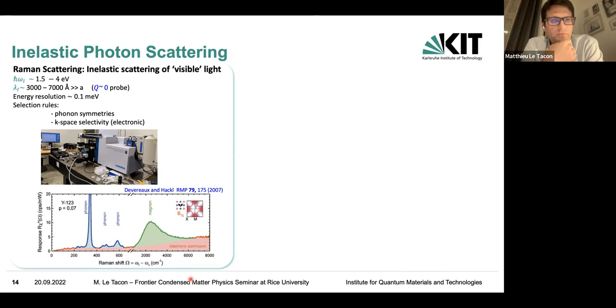The energy resolution is very good. I mean, it's like 0.1 milli-electron volt, and we do have selection rules which allow us to assess the symmetry of the excitation, and as well some k-space selectivity for the electronic excitation. That's a typical spectrometer. It fits on the table, and that's kind of typical spectra.